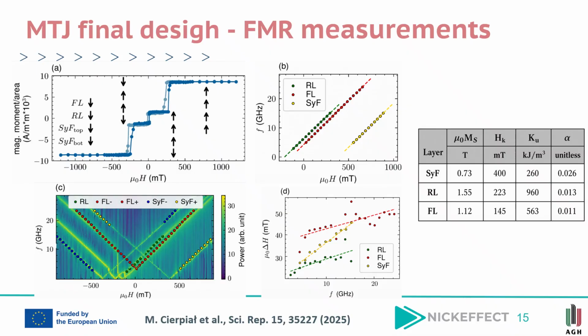Panel B shows the frequency versus field dispersion relations obtained from the FMR measurements for the RL, FL, and SyF resonance modes. The color map in panel C presents representative FMR spectra measured over a broad magnetic field and frequency range. Several resonance branches can be identified corresponding to the dynamic response of the individual magnetic subsystems within the MTJ stack. By fitting the dispersion relations, the effective magnetic parameters were extracted.